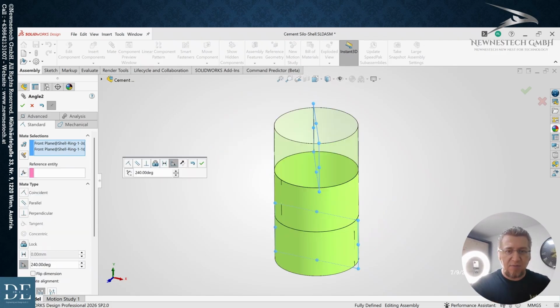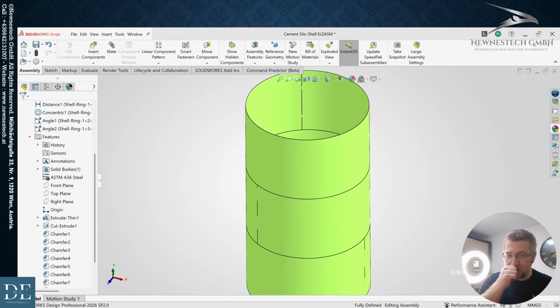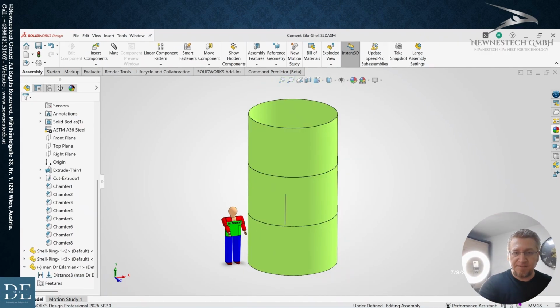Now we are bringing the third ring. Here you see that again, I'm considering the 1.5 millimeter distance to consider this 1.5 millimeter gap for root welding. That should be the distance between the two rings on the meeting edge. And then I'm also considering in the next slide the angle between the very first ring and the last ring, or the third ring, 240 degrees. Now we are making sure that there is a maximum distance of 120 degrees between all welding seams between these three rings. Perfect. This is how it looks like after putting these three rings together.